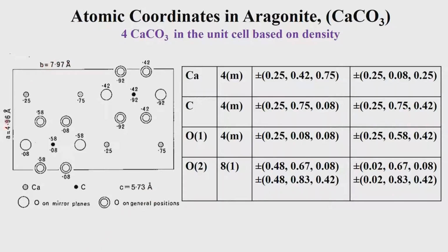A dot B cross C will give you the volume of the unit cell, from which we can determine the density as we discussed before. So, you see that the calcium atoms sit on the 4m position corresponding to the x value of plus minus 0.25 and the value of z is 0.75. But what is more important is that they sit on the mirror which is at plus minus 0.25.